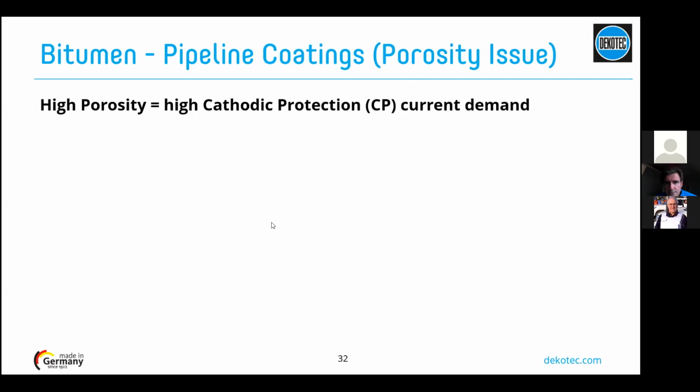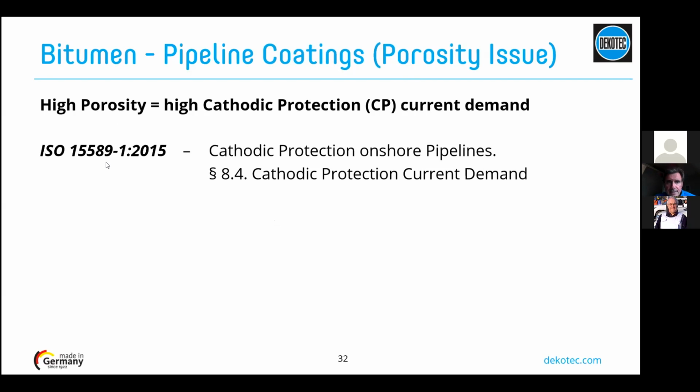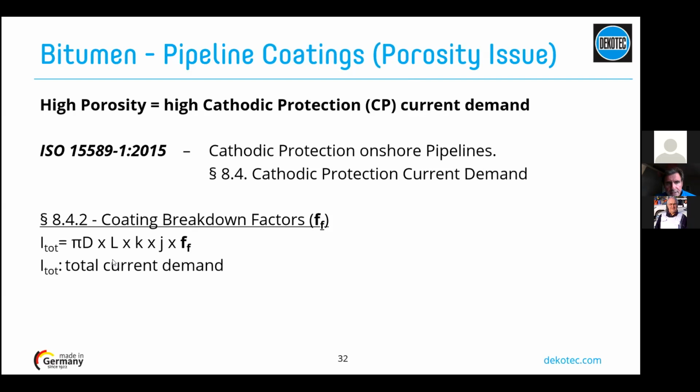And to understand the porosity, we have a look at this standard, which is a cathodic protection standard for onshore pipelines. Let's look at the chapter talking about the current demand. So chapter 8.4 is talking about the current demand for cathodic protection. Chapter 8.4.2 talks about the coating breakdown factor and gives the total current demand by this formula,